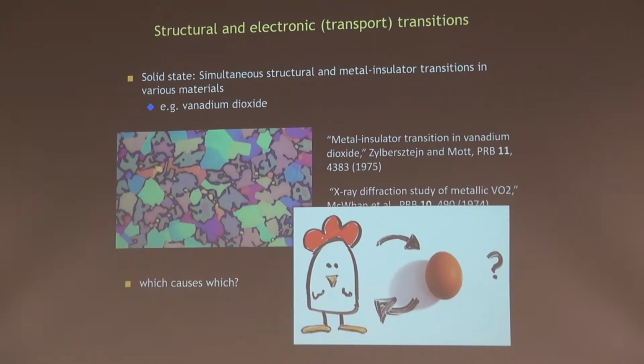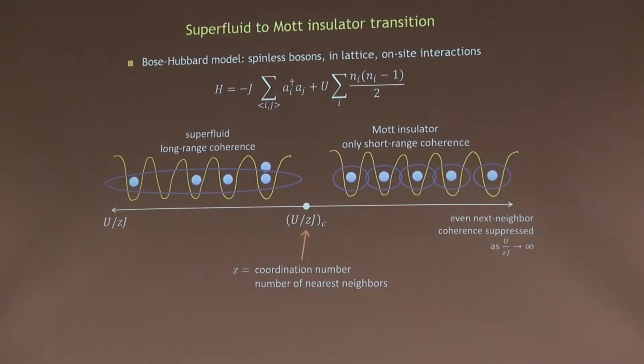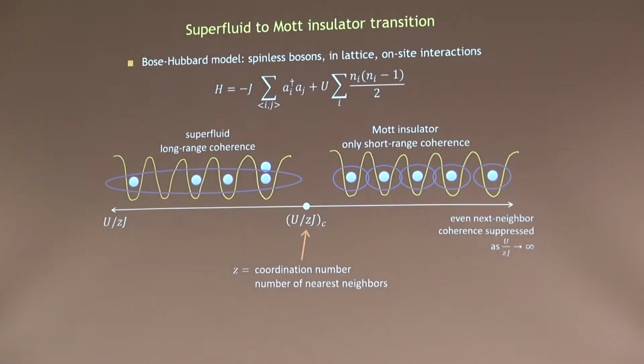But in these kinds of atomic quantum simulators, it's actually really easy because we control the structure of the lattice independent from what the atoms inside the lattice are doing. So we can drive a structural phase transition deliberately, and we can see whether it has an effect on the electronic sector, which is to say on the physics of the atoms that are trapped within the lattice. So for us, the phase transition that will occur is not a metal to insulator transition. We're working with rubidium bosons. So for us, the transition is a superfluid to insulator transition.